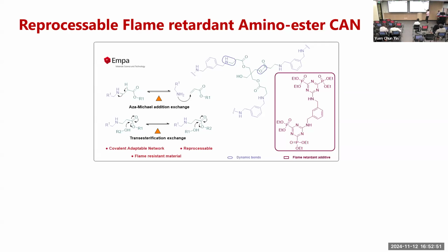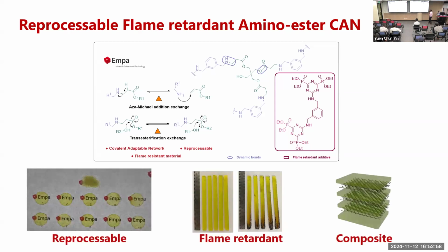What we did was we took this chemistry and we added our own additive to this resin, and we get a completely different kind of thermoset resin, which works by a very complex chemistry where you have two different dynamic bond actions happening at the same time. You get a recyclable material. You can see you can recycle it 10 times and you don't lose any mechanical property. It looks exactly the same as virgin material. And in this case, interestingly, you need only 0.6% phosphorus to get a V0 rating. Because in the past, I showed you some examples where you need 2% or 3% phosphorus. Here you need a very small amount of phosphorus. And of course, you can use this to make fiber reinforced composite.